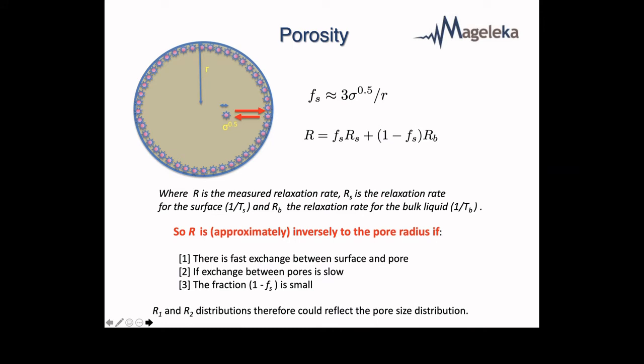Another thing that we've been looking at more recently is whether or not you can measure porosity. Now, a pore is a rather different object to the outside of a silica particle. But if you think of a pore like the picture I've drawn here, we have water confined in the pore, so there's adsorbed water on the internal interface, and that's in exchange with bulk water in the center of the pore. So the average relaxation time, again, tells us something about the surface area inside the pore.